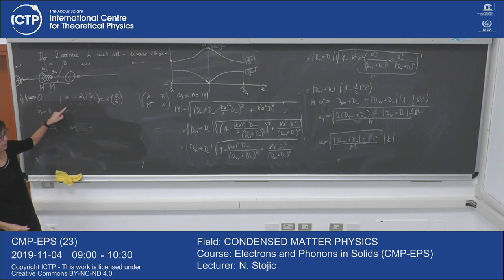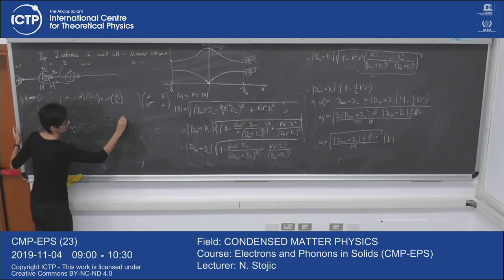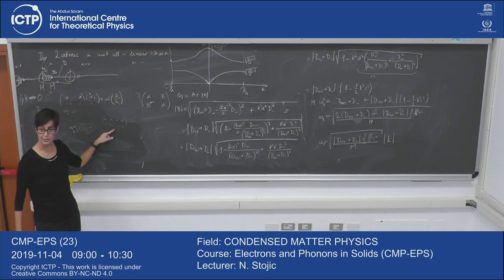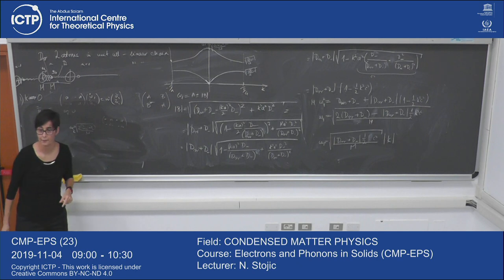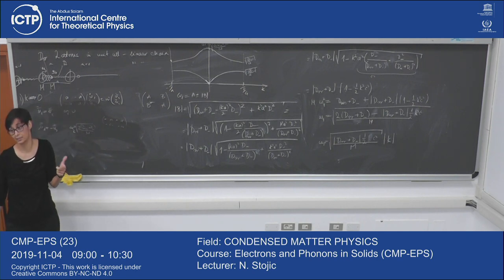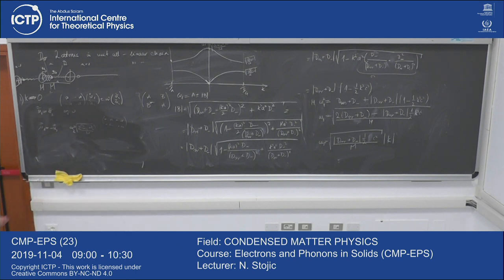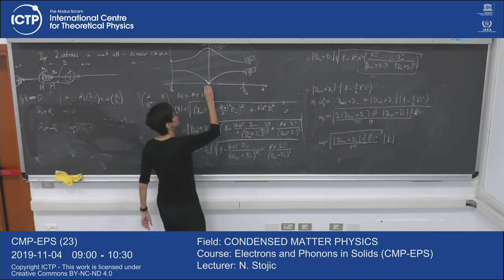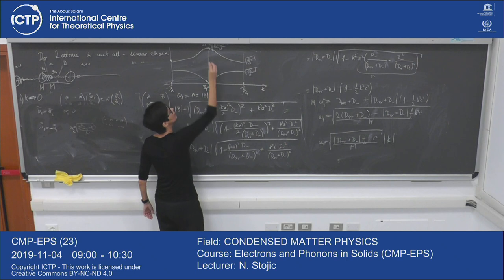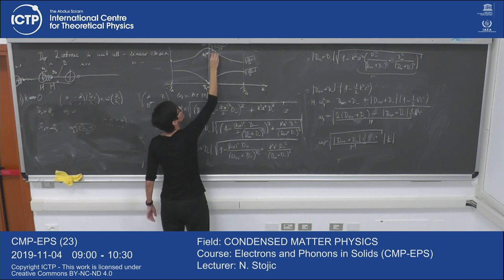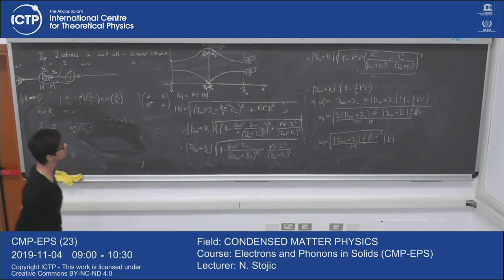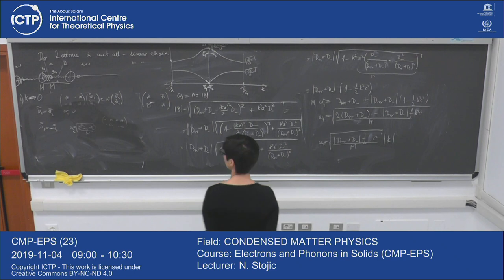In the case of k equals 0, we got this matrix, and it gave these two eigenvalues. When you have this, it was giving minus a here. And the eigenfunctions for this, to still have a zero, have to be opposite. You remember how to find eigenfunctions? That's kind of important, not just for this course, for everything. So the motion has to be opposite. Here U1 is equal to U2. Here they are opposite. And that's pi over a.